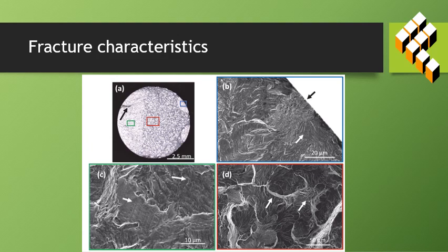For shorter cracks, a clean initiation and growth pattern is visible, and it is also possible to recognize on the fracture surface the occurrence of crack closure due to load ratio being equal to minus one, and also ductile features like dimples in the intergranular ferrite.